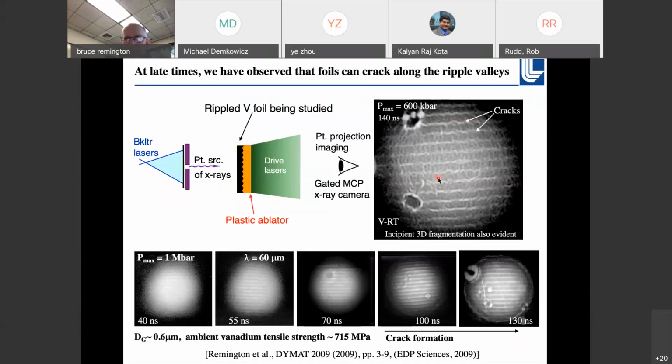But the contrasts are flipped around the wrong way, because bright in this image is low density, or little material left, and dark in this image means a lot of material, which would say the Rayleigh-Taylor spike would be the dark region and the bubble the white. But it's just the opposite, because it's the bubble that gets broad and the spike is narrow. So this image was completely opposite to what was expected.